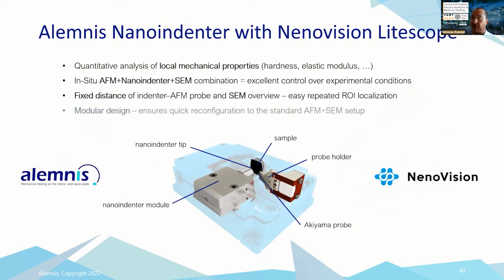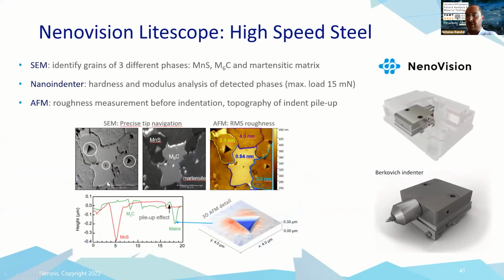We also have coupled our nano-indenter module with an AFM. And we heard earlier in Silke's talk about the use of AFM in situ in an SEM. Well, with this system, you can not only look at the zone in the SEM, you can image it with the AFM, and you can make nano-indentations in specific zones of your choice. So you can see here an example. This is a high-speed steel microstructure. You can see the backscatter images, the AFM image of the surface, and then we've made some indents in specific grains. So we're really moving towards correlative microscopy techniques where we combine mechanical properties, AFM topography, SEM, EDX, and try to combine all these in the same area with the same spatial resolution.